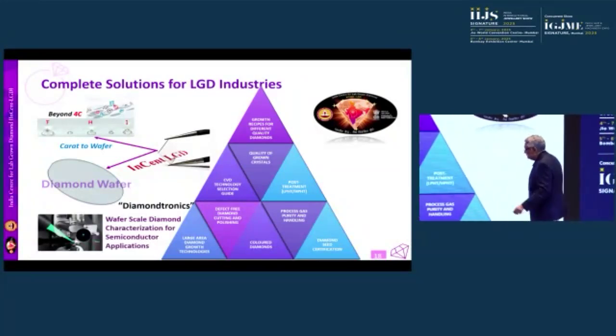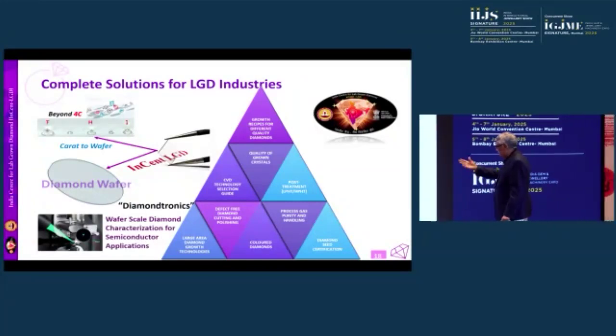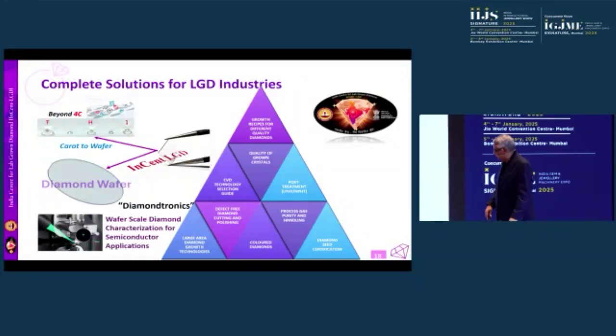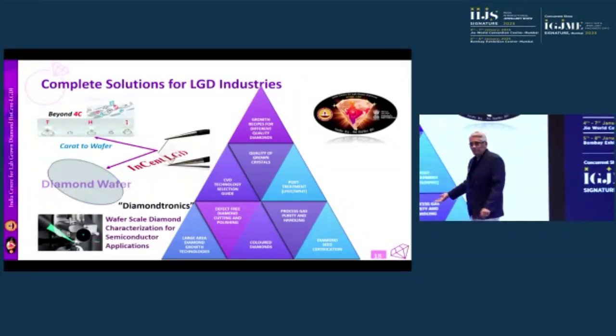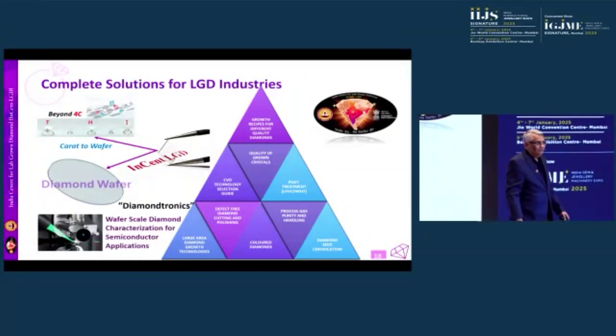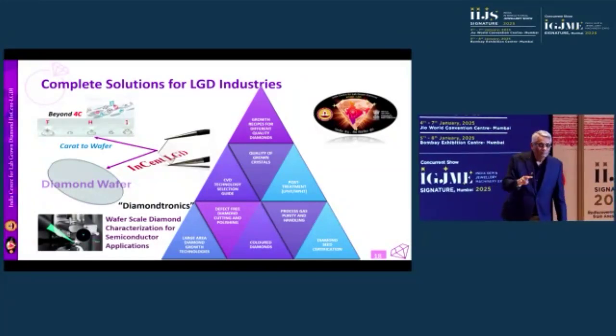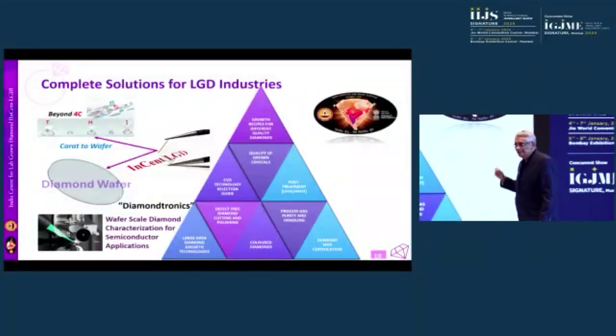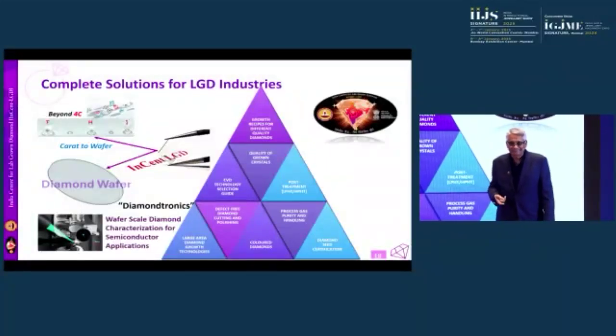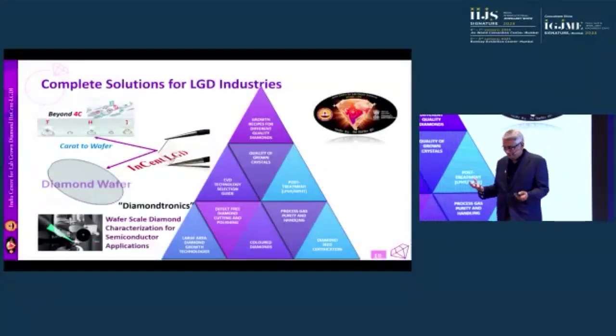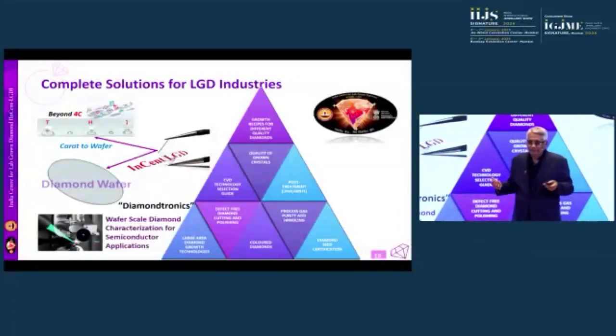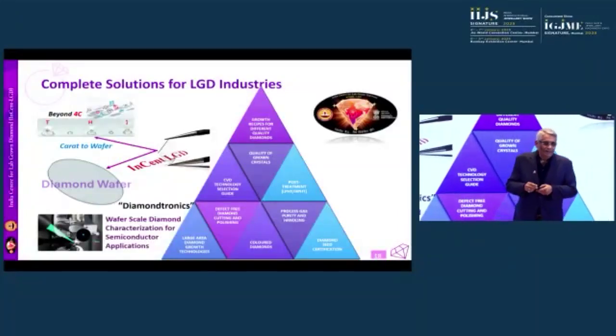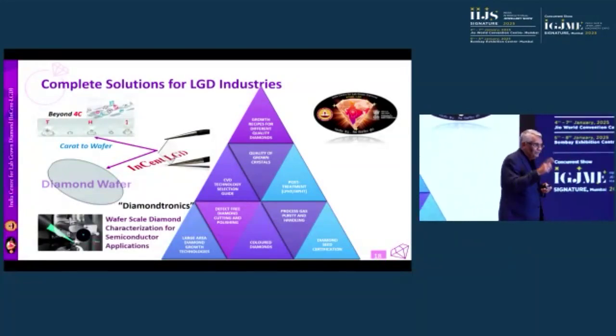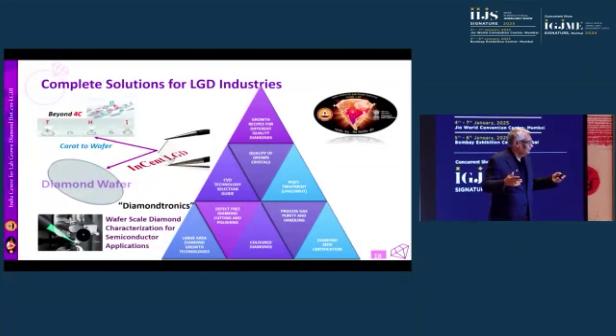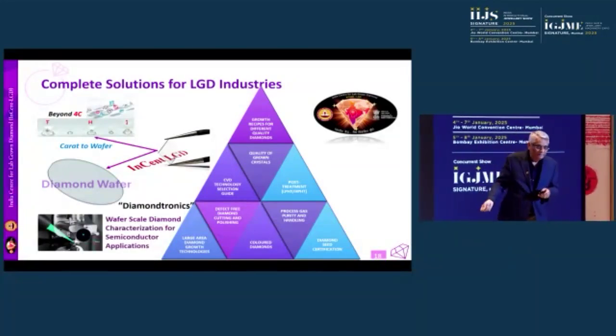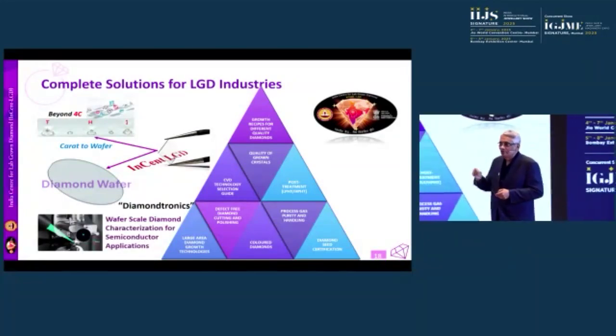Of course, you need to have a proper CVD technology selection guide. And I mentioned the importance of gas purity and all that. Of course, color diamonds, we are also seeing vivid colors here, beautiful colors. And colors can be obtained in two ways. Any gem crystal that is colored, the color comes because of defects inside. A pure diamond, a shiny white crystal, when it becomes colored, that means it has defects in it. And that means you're making these crystals a little impure, but that impurity gives you a beautiful color, it's okay. So you need to control them in a way that the original diamond structure is not lost.